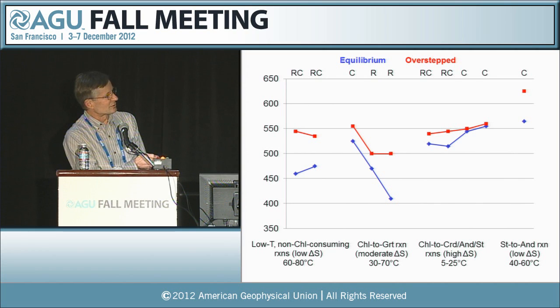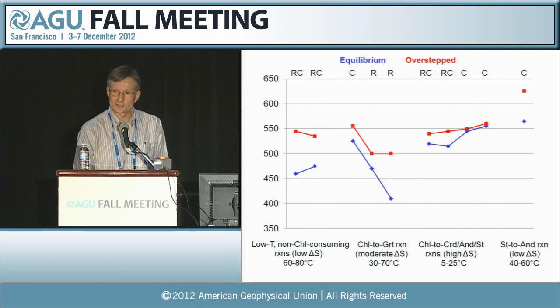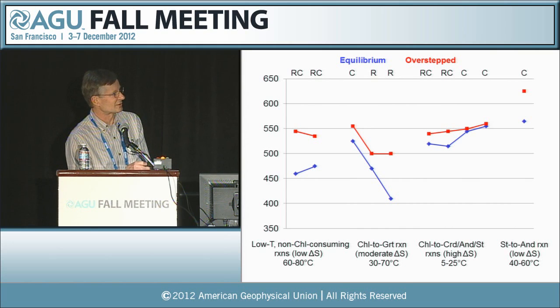And overall, you can see that there is a larger separation between the blue and the red for these low temperature non-chlorite consuming reactions. The amount of overstepping implied here is about 60 to 80 degrees. For the chlorite to garnet reaction, it's a bit variable, but overall it's a little bit less than for this one, though there is some variation. For the high entropy chlorite to cordierite, andalusite, staurolite reactions, the interval between predicted onset and actual occurrence of the reactions is the smallest. And then for this staurolite to andalusite reaction, even though it occurs at higher temperature, there's another fairly significant gap, which I would attribute to the low entropy change of that reaction.